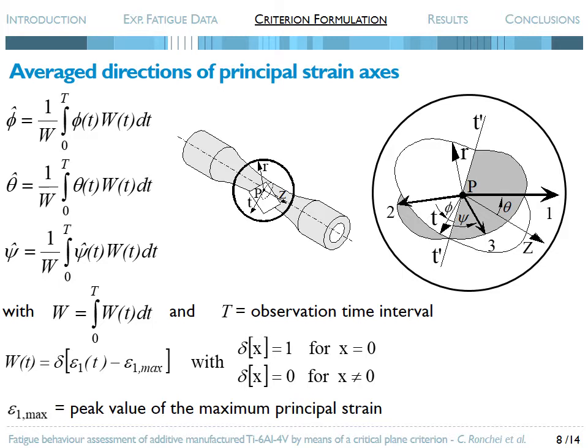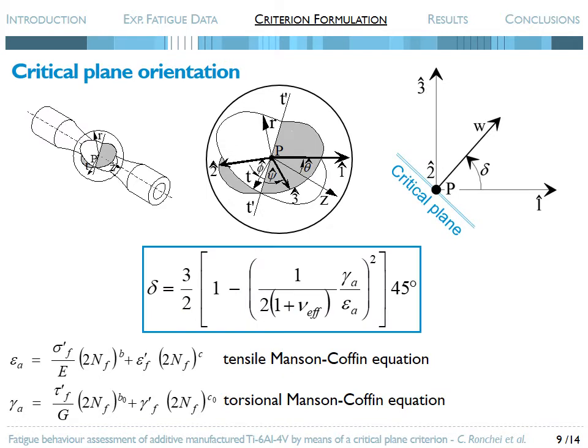2^, and 3^, coincide with the instantaneous ones at the time instant when the maximum principal strain ε1 attains its peak value over the loading cycle. Then the orientation of the critical plane, which is the verification plane for fatigue life evaluation, is defined by taking an off-angle δ in the principal average plane 1^, 3^.